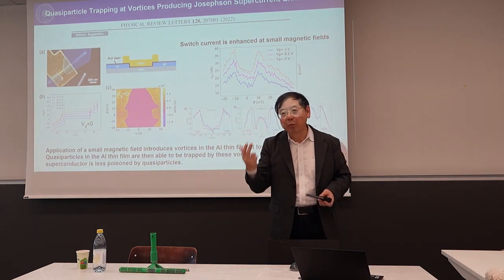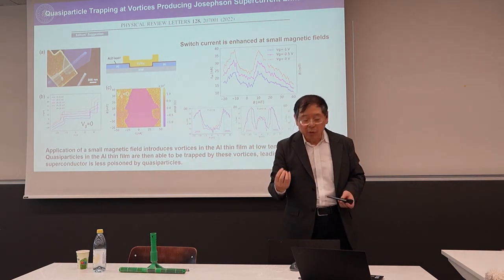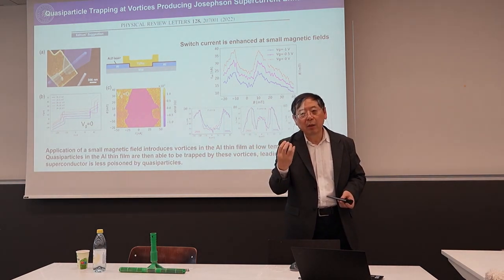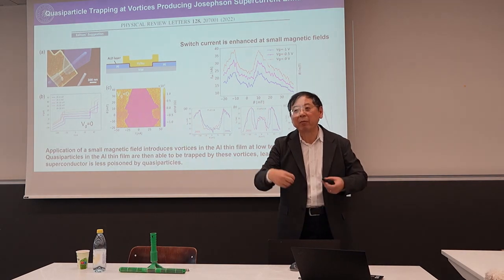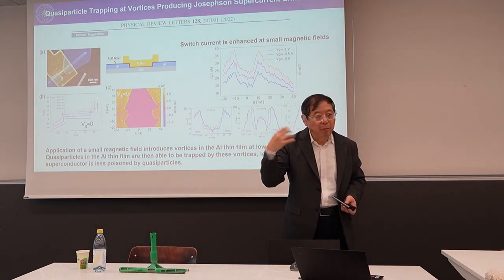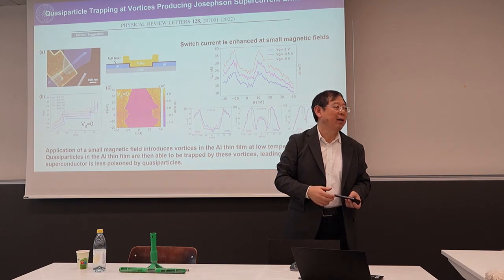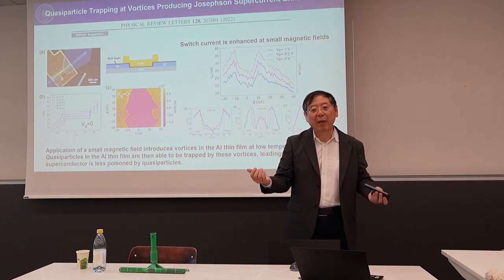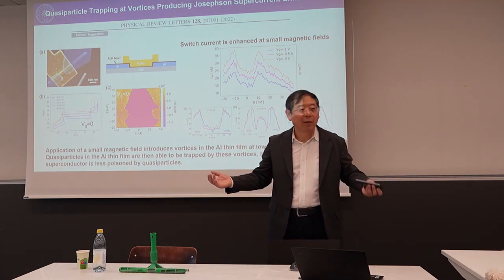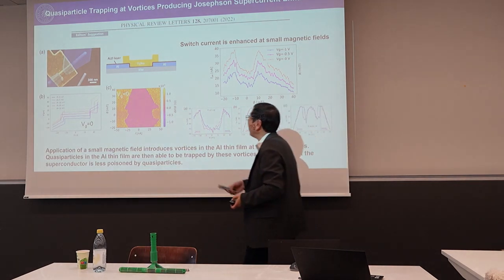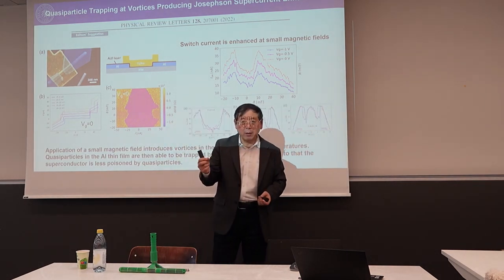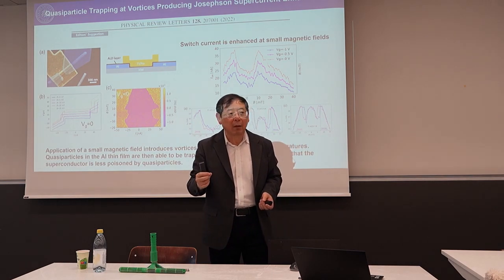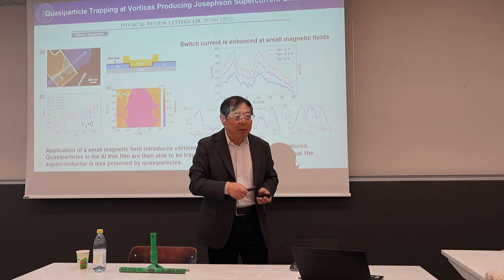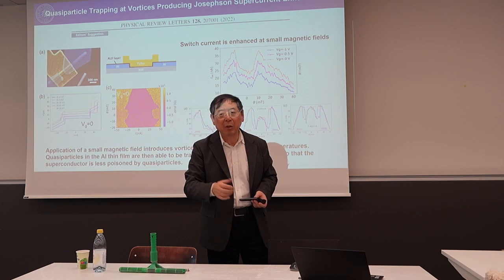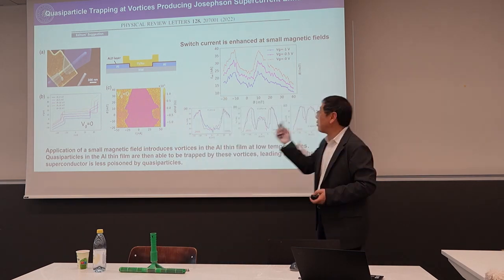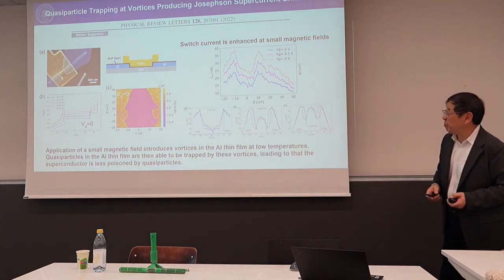When you increase the magnetic field, vortices form in the superconductor. And these vortices are very nice. They can trap quasiparticles, making the remaining part purely Cooper pairs. Then the Cooper pairs are no longer influenced by quasiparticles, so you can enhance the supercurrent. So this is a very nice work. It also gives an indication for the superconducting qubit community: maybe a small magnetic field may help them increase coherence time. So this is why the paper is also important.